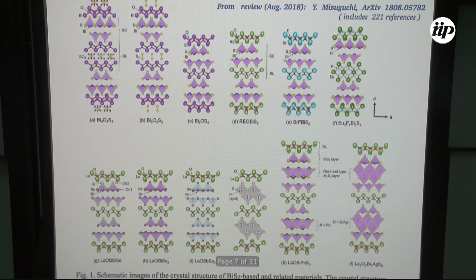And here you see how the family has grown. So here you see the first two compounds I was showing you are these ones. And for example, here you would have in the rare earth the lanthanum. This would be the other one in 2012. But then you see this kind of layers. These are the blocking, the conducting layers with bismuth S2, sulfur 2. And then you have all these other kinds of blocking layers, which depend a bit more on the material.